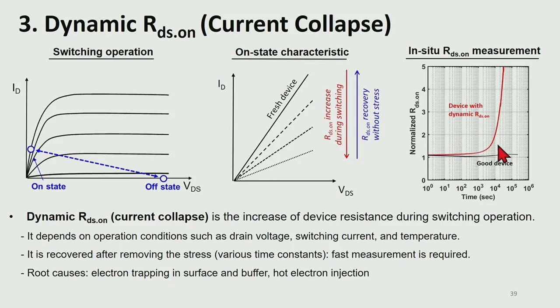So in the good device, the RDS,on drift is negligible, while in the bad device, RDS,on shoots up, so RDS,on is increased by a few times. This can cause a severe conduction loss increase and also cause additional self-heating. So the cause of the dynamic RDS,on is the electron trapping under high electric field stress. In the following slides, we're going to review a couple of different electron trapping mechanisms in GaN device and what kinds of process improvement is needed to suppress them.